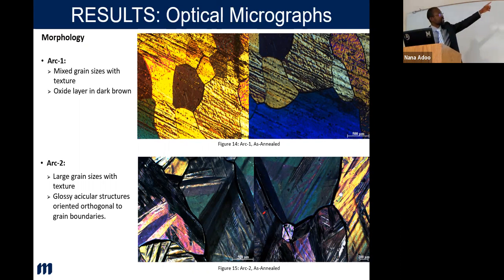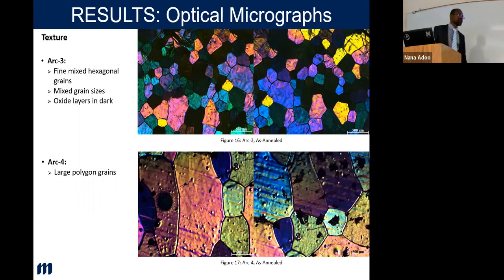Arc 1 had a transformation and hysteresis, a very large hysteresis, but you don't even see martensites here. And why? Because the transformation temperatures are actually so low, so you don't expect to. 2 is showing you, which is even at room temperature or something similar to that, but you don't see any transformations. And Arc 3, very fine grains, hexagonal by looking at it, but there's nothing showing for that. And this was one of the hardest materials actually I encountered when I was cryomilling. It's not ductile, very brittle, but very hard as well, so never transformed.